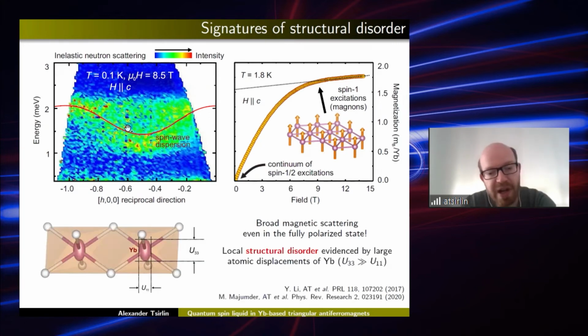Why could it be? One possibility is that there is some underlying structural disorder that leads to the random magnetic couplings. And we tried to explore this scenario further. Indeed, when we did a careful structural study, we have seen some unusual feature. This is the atomic displacement parameter of ytterbium. And you see that even at low temperatures, the ellipsoid is very asymmetric, which is strange because the ytterbium is sitting in the ideal octahedron, so the vibrations of the ytterbium should be symmetric, but they're not.